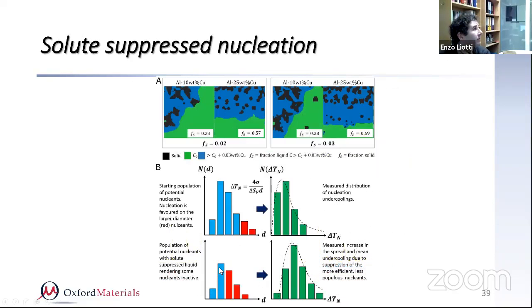And this was explained by looking at the effect of solute suppression. Solid suppression is a concept that showed that by increasing the solute content, you increase the size of the solute suppressed zone. The solute suppressed zone takes place because there is partitioning. So when you have a solid forming, it will segregate. In the case of aluminum, for a hypoeutectic alloy, it will segregate solute into the liquid. In the case of a hypereutectic alloy, it would be the opposite. It will actually deplete the liquid of solute.